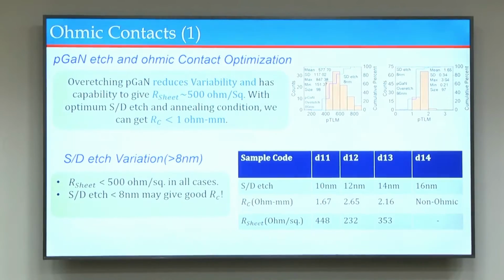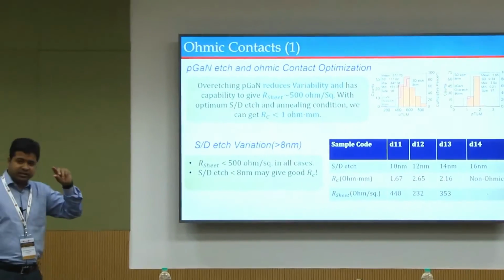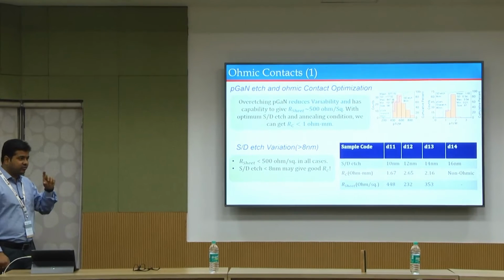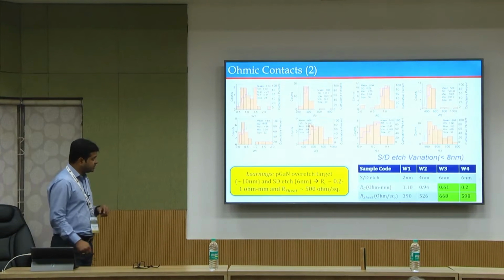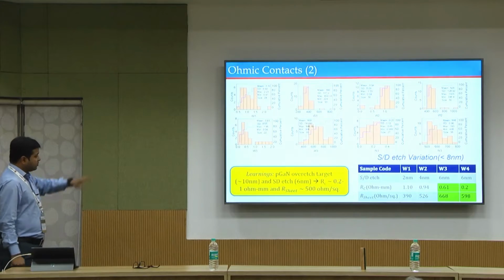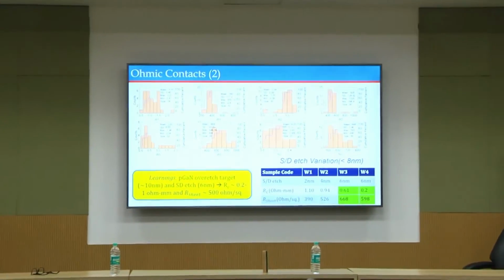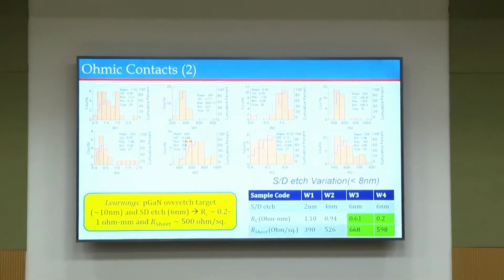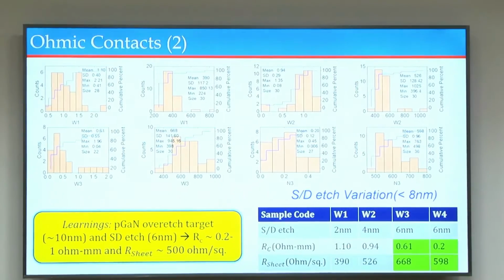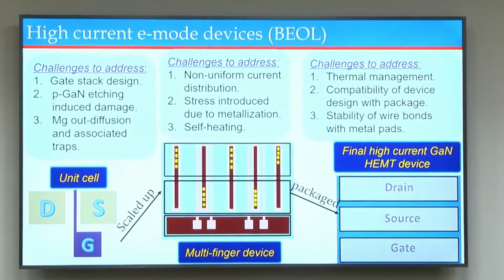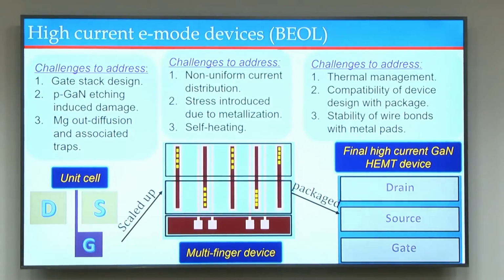Similarly with the contact, you have to find the right recess depth, and if you don't recess, you will never get an ohmic contact. Only if you recess you get ohmic contact, but then you have to have very tight control on the recess depth. So you have to do a lot of optimizations and make sure that statistically these numbers are giving you the performance parameters, not just getting 1 or 2 data points.